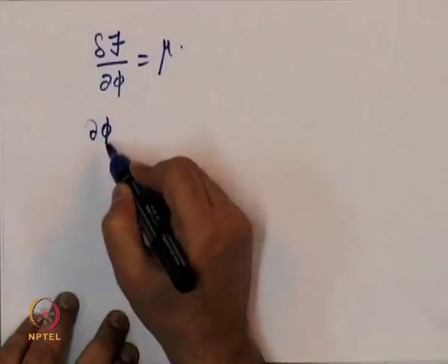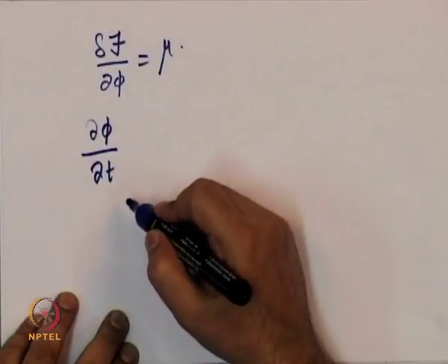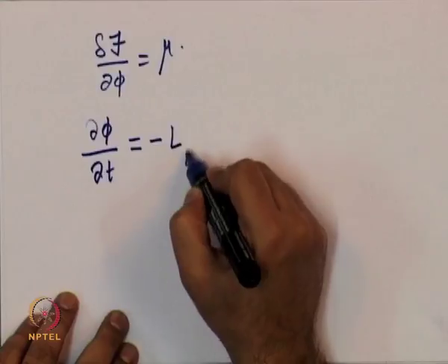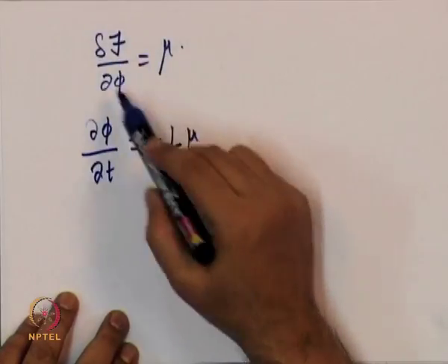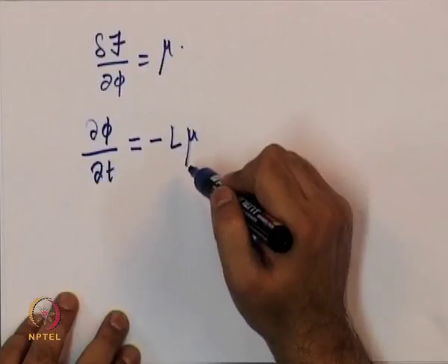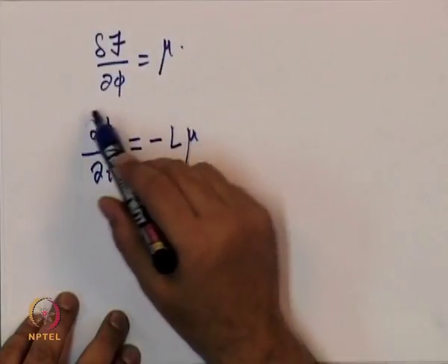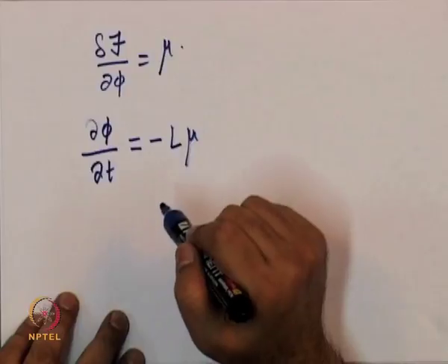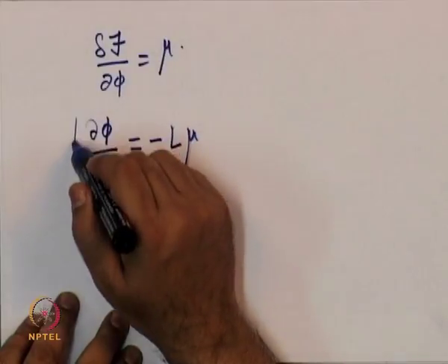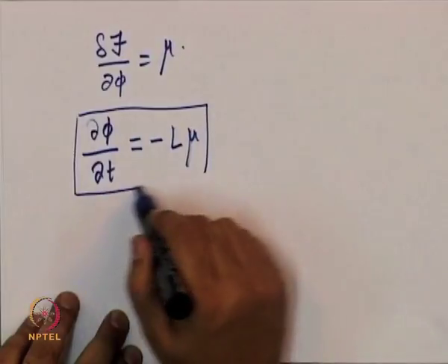At the beginning you might have half of them having red atoms at the center, and towards the end of the simulation maybe everything has become blue at the center or everything has become red at the center, either can happen. So, there is no conservation law. In this case we say that the order parameter phi evolves in such a way that the chemical potential that you calculate using this becomes the same everywhere. That is basically the constitutive law, and this is known as the Allen-Cahn equation.